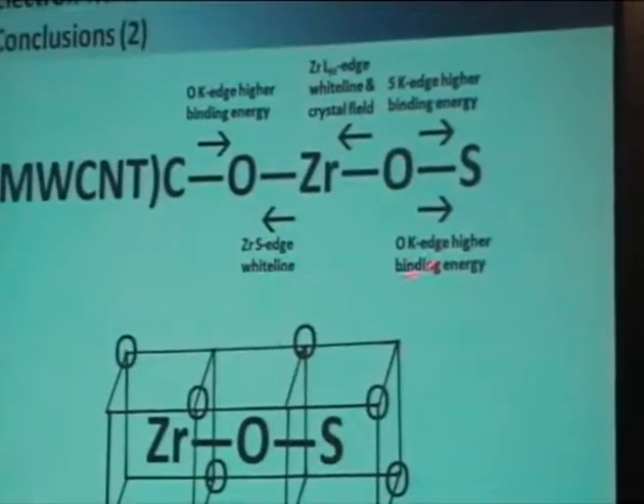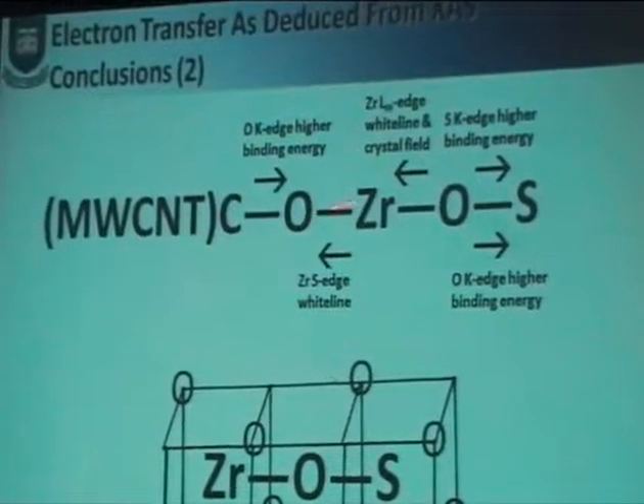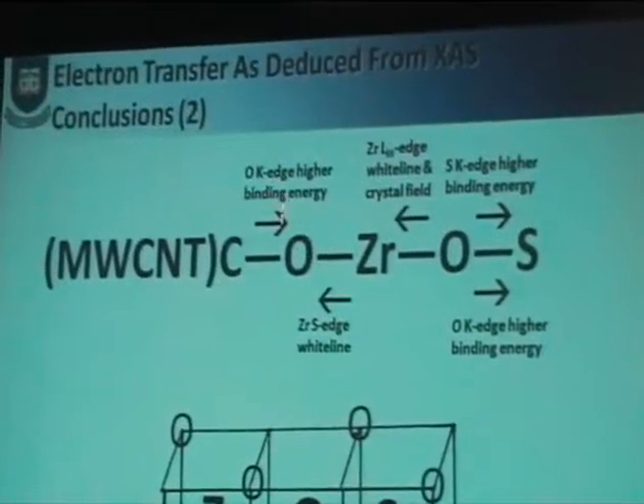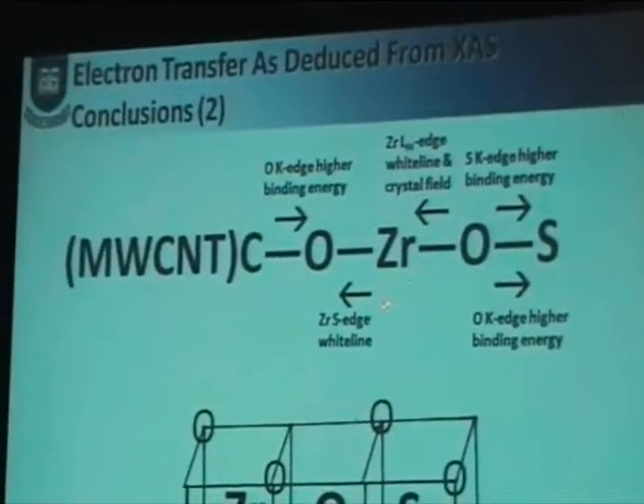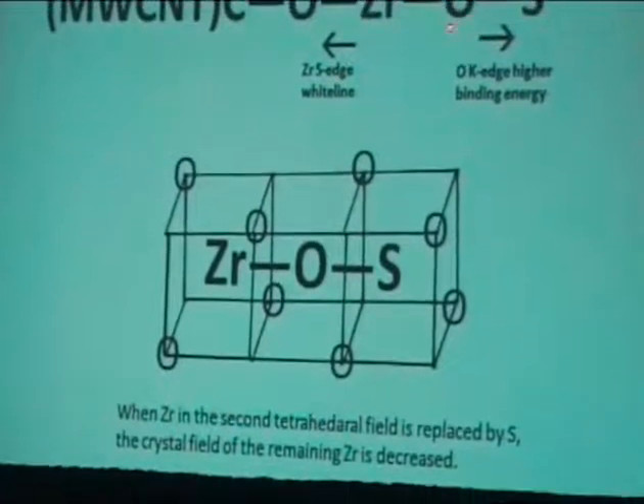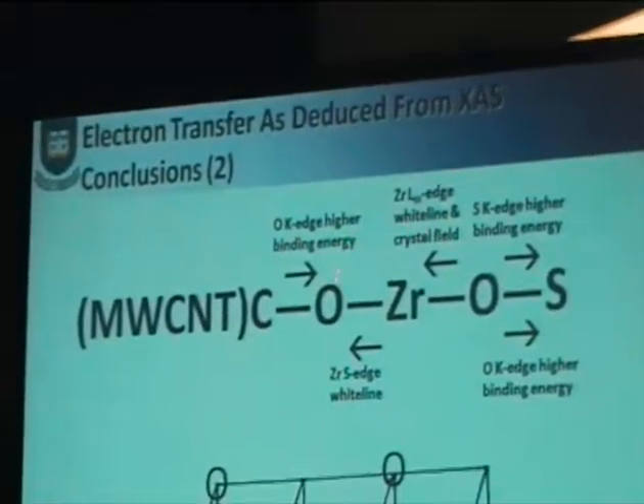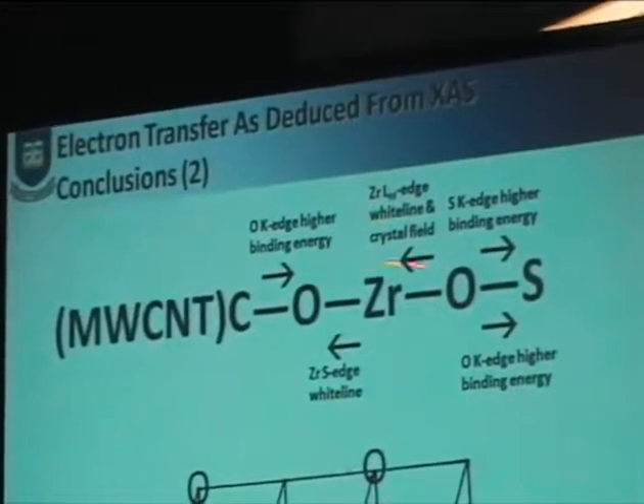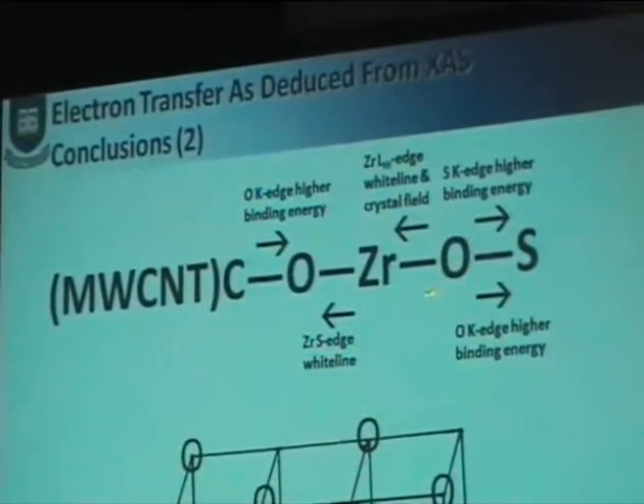So the net, if you look at this, is that this oxygen at the interface is gaining electron density both from zirconia and from carbon. This oxygen is losing electron density to sulfur and zirconia. So the real difference is just the net change between the sulfur and the oxygen.